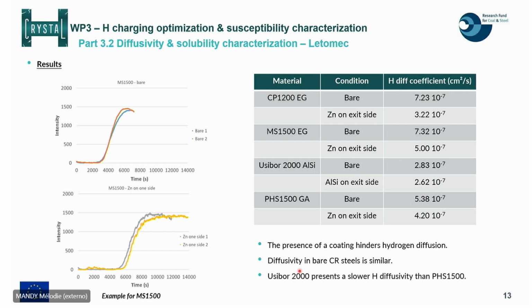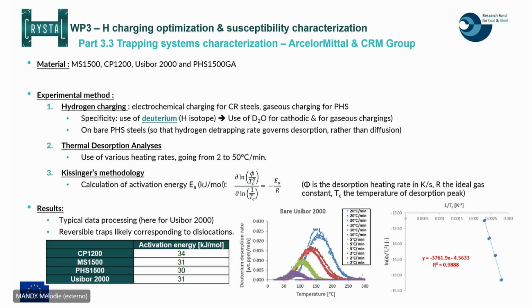So this leads me to the final part of this presentation. A last thing that we had to do in this part was to characterize those materials in terms of hydrogen traps. So what was performed here is globally the same methodology as just before. Firstly, we charged the samples with hydrogen. Again, it was performed using electrochemical charging for cold-rolled steels and using gaseous charging for PHS.